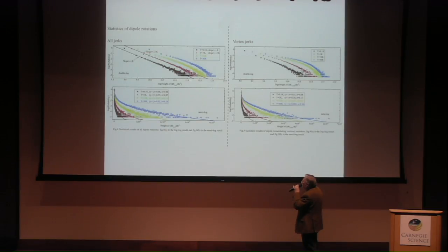So in the crystal, all the stuff which is happening at low temperature here is scale invariant. But if you look at the vortices, you can see it's not scale invariant, slightly bent, and at higher temperature it's massively bent. And that means the temperature effects are seen primarily at this point in the vortex lattice, and they're not seen in the domain lattice. So again, you have a separation here of energies. I mean, the energy of the vortex is very low, and the energy of the domain boundaries are very high. So I stop with that. Thank you very much.